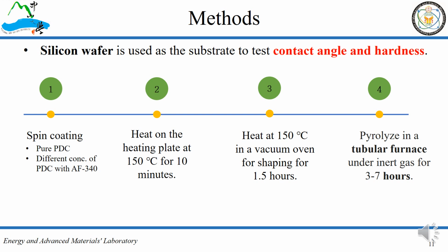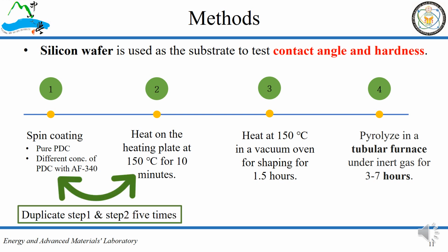First, pure PDC and different concentrations of PDC with AF-340 are spin coated on the silicon wafer, and then the coated wafer is put on the heating plate at 150 degrees Celsius for 10 minutes. Repeat step 1 and step 2 five times to form an even coating layer. The next step is putting the coated wafer in a vacuum oven for shaping for 1.5 hours. The final step is pyrolyzing in a tubular furnace under inert gas for 3 to 7 hours.